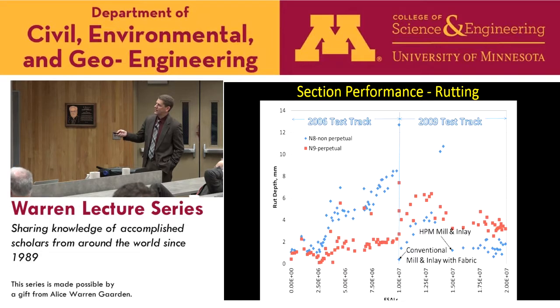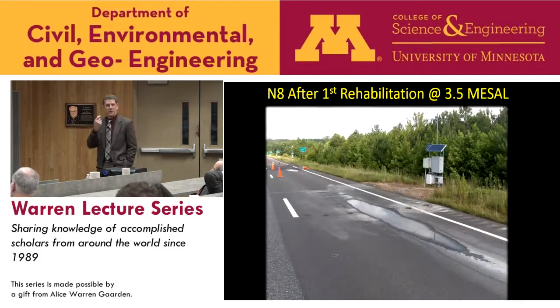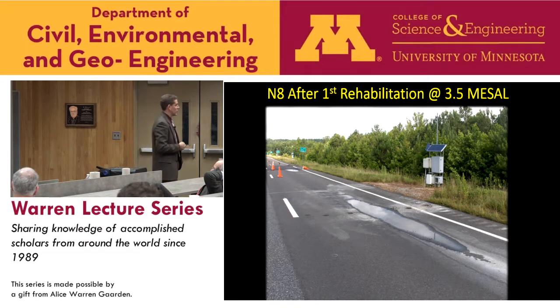Rutting, again, the perpetual section topped out somewhere about a quarter inch, which was good. The non-perpetual had a lot of rutting, and then had rutting again after we did the first mill and inlay, and then it kind of leveled off. What does it look like? Well, this is the non-perpetual section. We've got cones out. That's always a bad sign. And water standing in the section is not draining. It's obviously not performing very well.